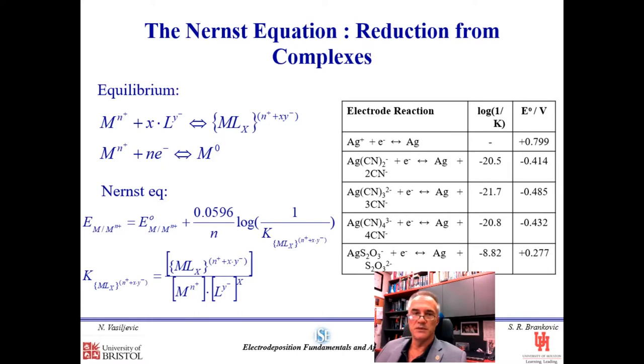When we talk about equilibrium potential defined by the Nernst equation, we have to appreciate the fact that we could have complications related to the stability of the metal ion due to complexation in the solution. So if we have strongly complexing anions in the solution which form a stable chelation around the metal ion, then the reversible potential could actually be very different. The Nernst equation is then a little bit modified and is a function of the reversible potential of the metal ion in standard conditions, and then there's a logarithmic term which includes the stability constant of the metal ion complex with the particular ion defined here. There are many examples to keep in mind, but here I just give you in this table the example of silver complexation with cyanide ions, which can shift the reversible potential of silver more than 1.2 volts in the negative direction.